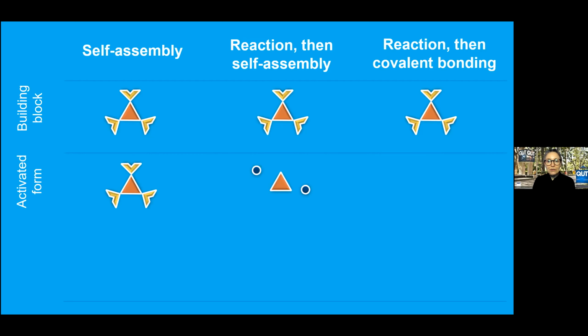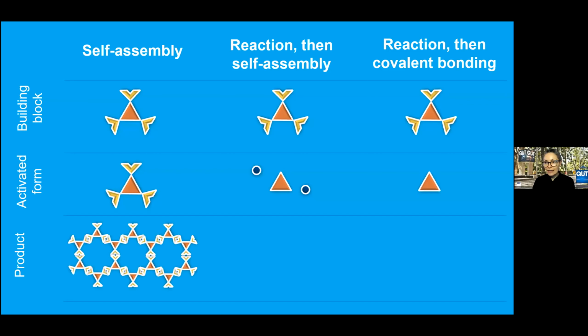We can also do this reaction then self-assembly approach, in which we will alter the molecule through some sort of surface confined reaction, and then it will undergo non-covalent interactions to assemble. And of course, we can also initiate covalent bonding following the activation of the molecule. So we end up then with different products. And here would be a typical self-assembled structure where the molecular building block has been retained intact.